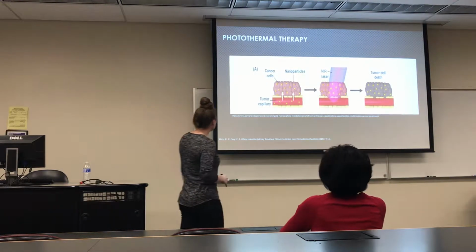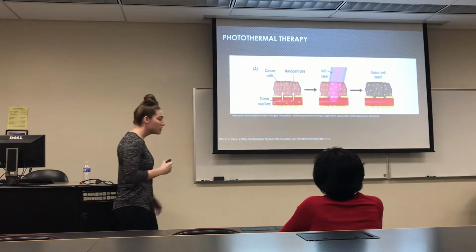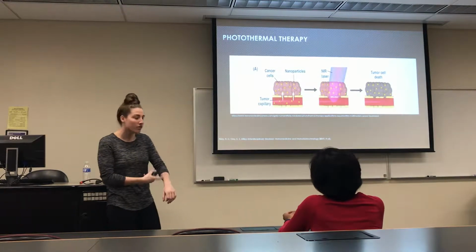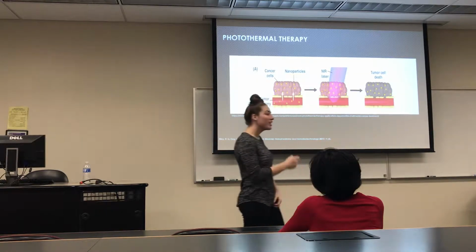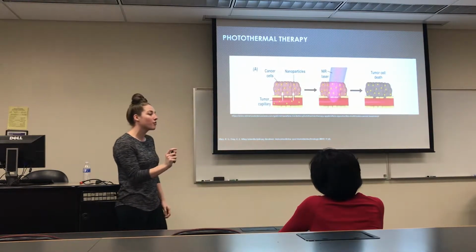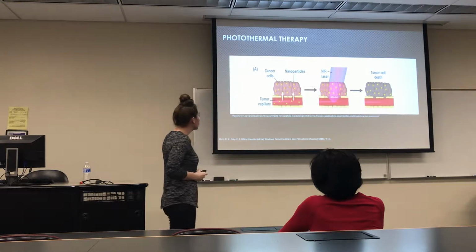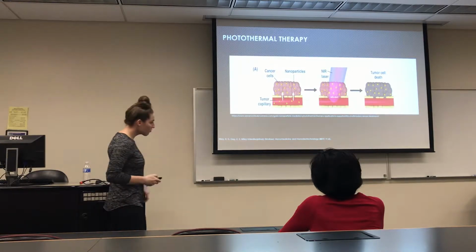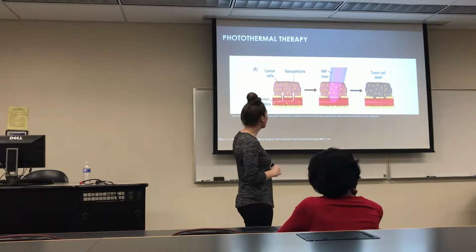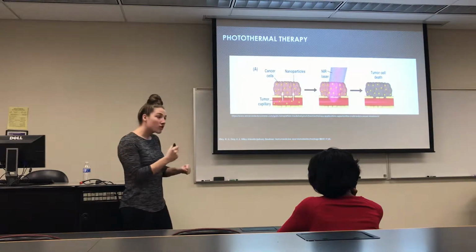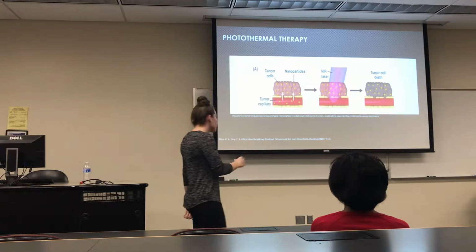So photothermal therapy is described by Riley and colleagues as an introduction of the nanoparticles into the tumor tissue. So this can be direct injection or an intravenous injection, and recognize if you're going to be giving it through the vein, you're probably going to need a specific receptor on the outside of that nanoparticle to actually get to the tumor site. However, what we're hoping for is aggregation of these nanoparticles within those tumor cells. And then following that, we can actually hit it with a laser that has a wavelength in that near infrared region and cause vibration of those nanoparticles.